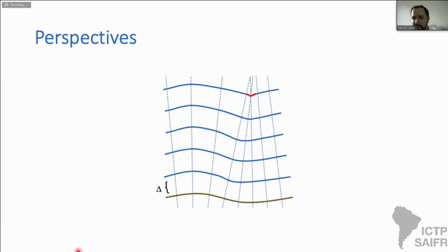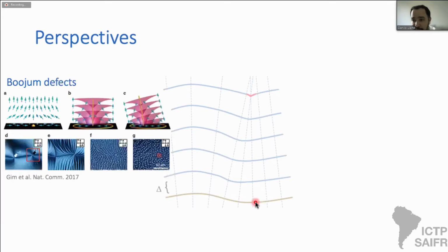But now suppose that the first layer here is not really a layer, but a hard boundary confining this magnetic liquid. It's then very easy to see that non-trivial boundaries can lead to a very interesting interplay between this extrinsic geometry of the confining substrate, the intrinsic geometry of these magnetic layers, and the energetic cost to compress or dilate the spacing between the layers.